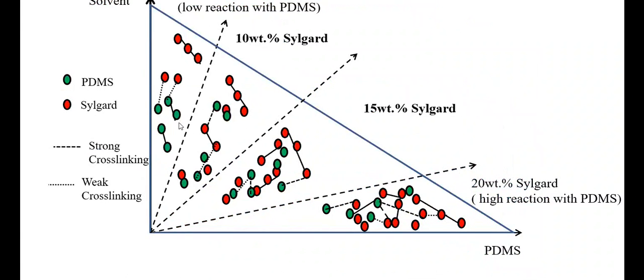So now this is the reason when we are going above, when the PDMS is increasing over here. The x-axis shows the PDMS and the y-axis shows the solvent. So when the Sylgard increases by weight percentage from 5 weight percent to 20 weight percent, at 5 weight percent a low reaction of PDMS has taken place. Ideal is 10 weight percent of Sylgard, and above that is the high reaction of PDMS with Sylgard, which increases the cross-linking density, I would say.